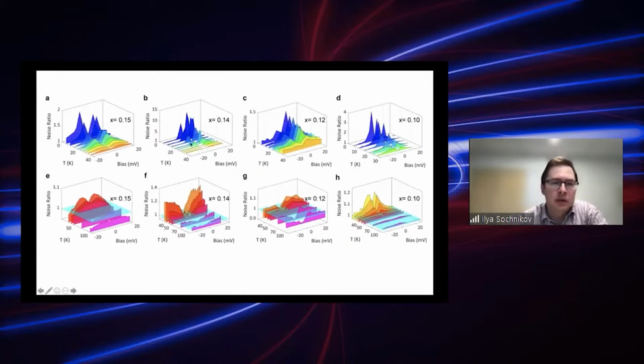This is a data set that I like to look at. Just to guide you, if you go to the paper, this is in the supplementary material, but I like this picture most because it shows that, for example, at the optimal level, x equals 0.15, you see this additional noise at lower temperatures. But then also, if you go to temperatures like 50 Kelvin and even above, you still see the noise. So this is not just some inclusions that may have slightly higher critical temperature. These are really additional noise features that extend beyond the critical temperature.